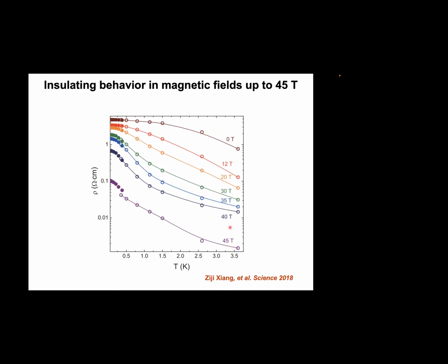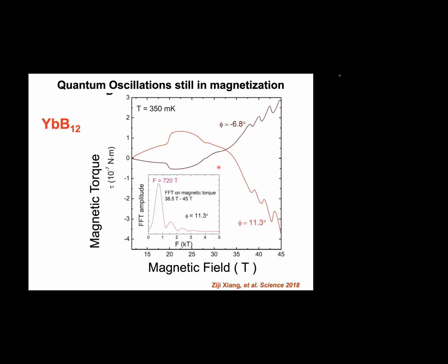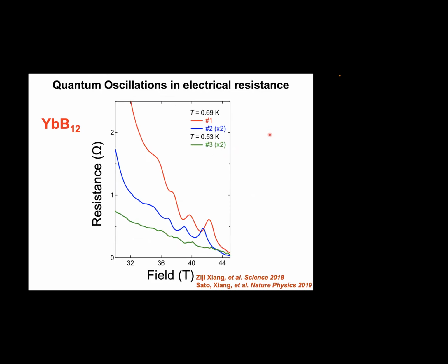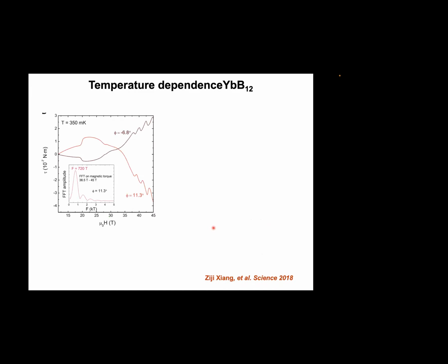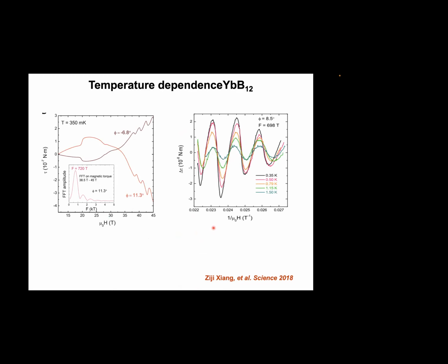And yet, in the field range below 45 Tesla, when we look at magnetic torque versus magnetic field, we have this nice size of wiggles in magnetization, which is again repeating what we have observed in SmB6. Magnetization shows oscillations, right? Now, when we look at resistivity, finally, we observe oscillations in the raw data, resistance versus magnetic field, and we have this nice size of wiggles. It's a charge process.